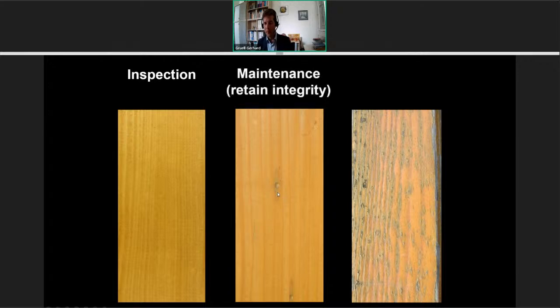There is a small defect, probably by hail impact, with some very slight discoloration around it, and there are a few cracks in this sample. And in this stage, you would need maintenance to retain the integrity of the coating. As long as the adhesion of coating here around this hail impact is not disturbed too much or still in good conditions, you can put a maintenance coat on top of it and retain integrity and prolong the service life of this coated surface very much.